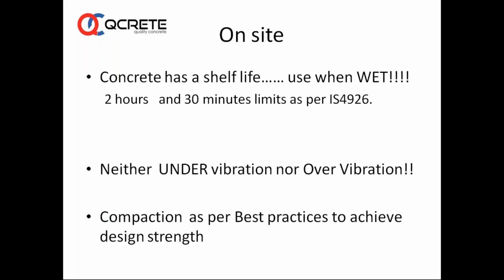So in short, what I want to tell you is, for higher grades of concrete, you should be very, very careful about the time of placing. You cannot prolong the concrete setting time for a long time, and hence it has to be used quickly. Otherwise, the disturbance you are causing to hydration will take a toll, and the durability will be affected. Such concretes may also exhibit plastic shrinkage and settlement cracks. So strength also may be affected. So you need to use the concrete in time to keep your concrete towards durability.